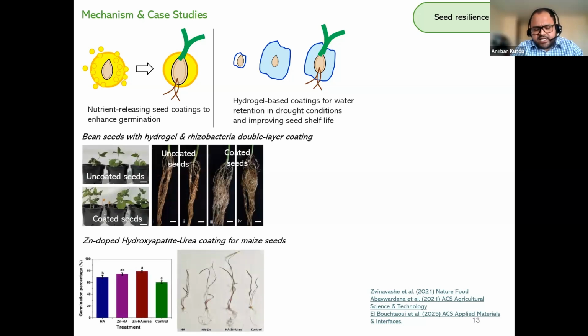And a lot of interesting studies have been done in this space. The first one, one of my favorites, is a double layer seed coating. This provided moisture, but it also provided a particular species of bacteria called rhizobacteria. Now, rhizobacteria are very important bacteria which are present in the root nodules of plants, and they help in fixing nitrogen. So the authors said, if we could have a protective layer or a bilayer that not only provides an enabling moisture environment to the seed, but also specifically provides an environment rich in rhizobacteria, then it can enhance the germination of the seed over time.